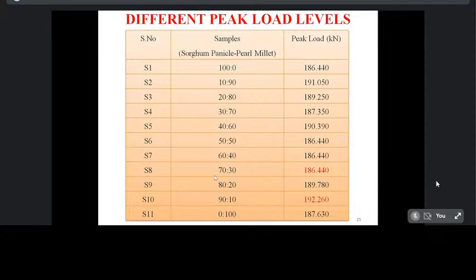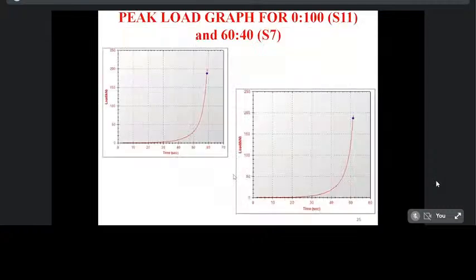Sample S1 had the minimum peak load of 186.44 kilonewton, along with S6, S7 and S8, and the maximum peak load was attained by sample S10. Why do we get these different peak loads? The reason for the variation was the particle size of the pearl millet. We have taken two materials here, sorghum panicle and pearl millet. The particle size of the pearl millet was finer than the sorghum panicle, so the spaces between the sorghum panicle particles were closely filled by the finer pearl millet particles. This is the reason we get different peak load levels during the production of the agro biomass briquettes. This image shows the peak load graph for sample S11, which is 0% sorghum panicle and 100% pearl millet, and sample S7, which is 60% sorghum panicle and 40% pearl millet.